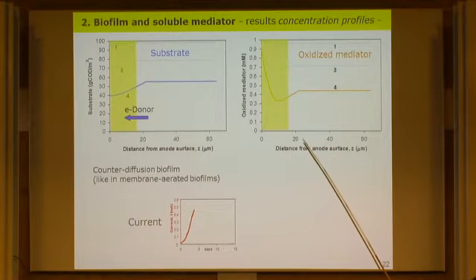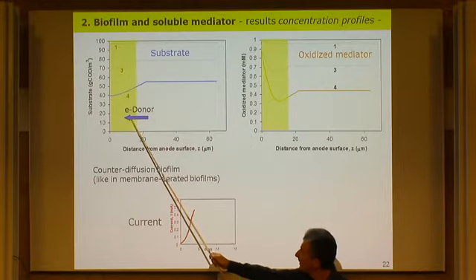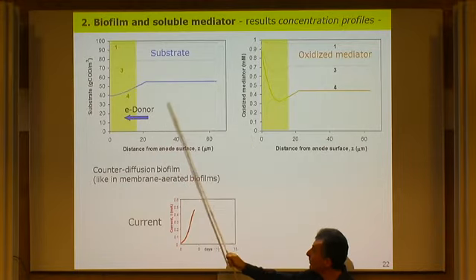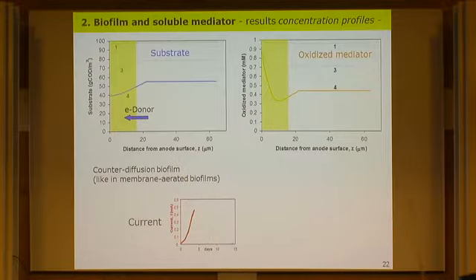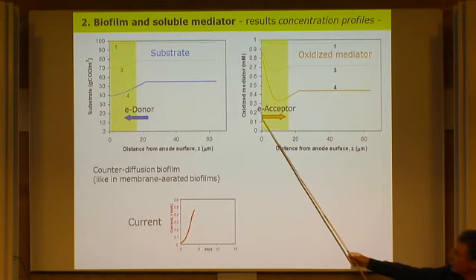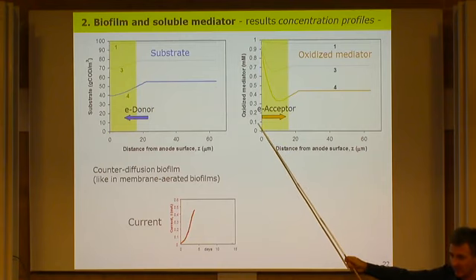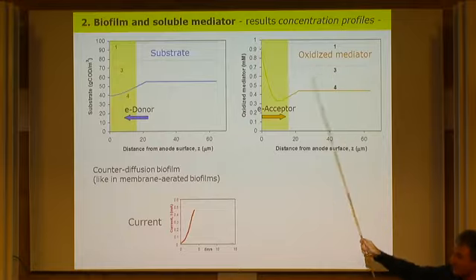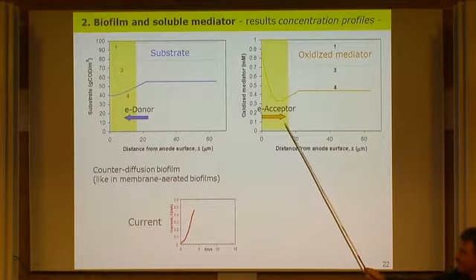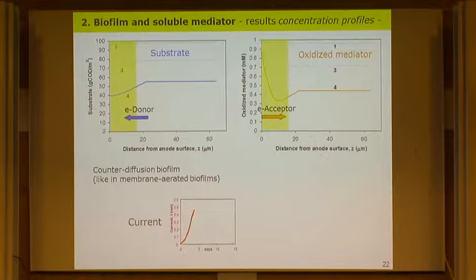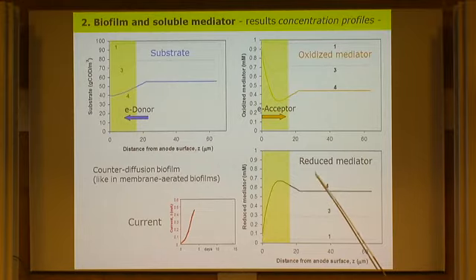It's a typical counter-diffusion system, like the one we studied in the COMSOL course. One part of the redox couple, the electron donor, comes from the liquid and diffuses in the biofilm, and the electron acceptor is generated here at the electrode. It's the oxidized mediator coming from the electrode. So it's counter-diffusion in this case. That's why you see this minimum here. Where they meet, you have the reaction taking place. And this is the reduced mediator, exactly mirroring the oxidized form.